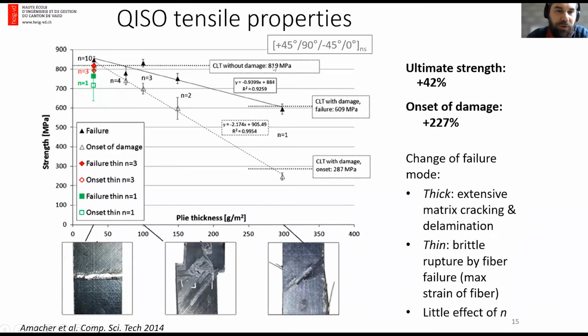What is also interesting is that if we compute the strength of the laminate based on classical laminate plate theory, considering no damage and considering that failure occurs when the 0-degree ply fails, we reach exactly the values that we've tested. So this means that we can reach the theoretical strength of a laminate if we use sufficiently thin plies. While for thicker plies, the behavior is dominated by delamination and transverse cracking. For thin ply, it behaves like a homogeneous solid that is linear elastic until final fracture. So this is very interesting.